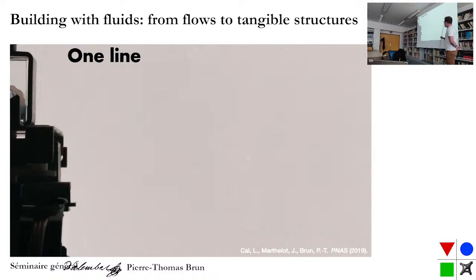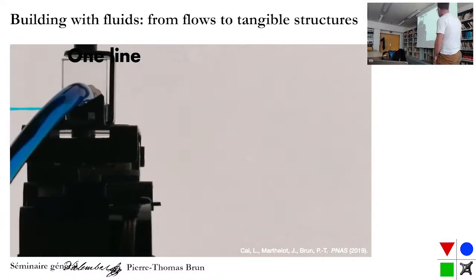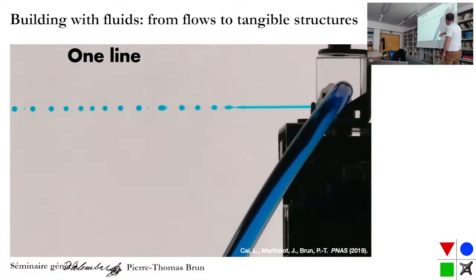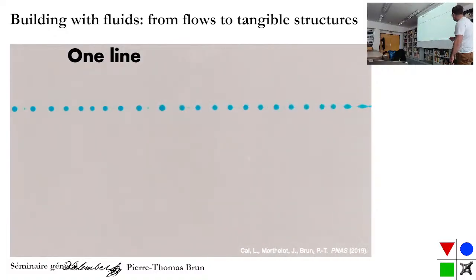So this is just an example. Here, what you see is a bath of oil, and that's a top view of the bath. And what you're about to see is a needle that's dragged inside this bath, and we're extruding glycerol. Glycerol and oil are not miscible, right? So we're drawing a line of immiscible fluid inside the bath. So without surprise, what happens is exactly what happens when you open the tap. It breaks due to the Rayleigh-Plateau instability, okay, and you have a collection of drops.